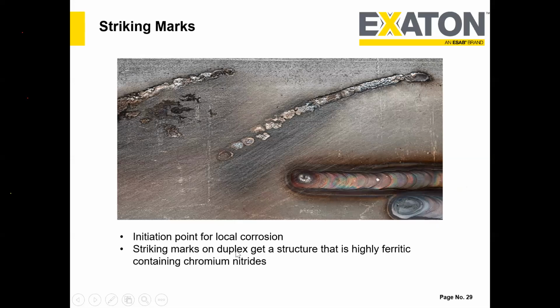Arc strike is really dangerous. It is basically the initiation point for local corrosion. When you do an arc strike, it gives instant melting and a very high cooling rate. Because of the very high cooling rate, it contains a lot of chromium nitride. As I told you, if you have a faster cooling rate, it forms chromium nitride. So it is highly ferritic because it does not have time to transform into austenite. It has a lot of delta ferrite and at the same time contains a lot of chromium nitride. So it is dangerous.